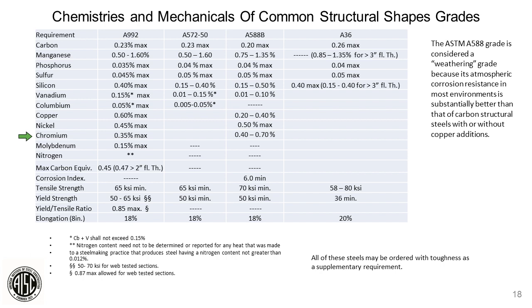Molybdenum, again, it's residual. We've got to minimize that. Get too much of that, steel gets very, very brittle. So we control that through our scrap recipe. We talk about nitrogen. That's just, again, so many ppm that we get in the steel making process. We test it on an analyzer. We'll talk about that later. But it's not specified, but it's present in the steel.